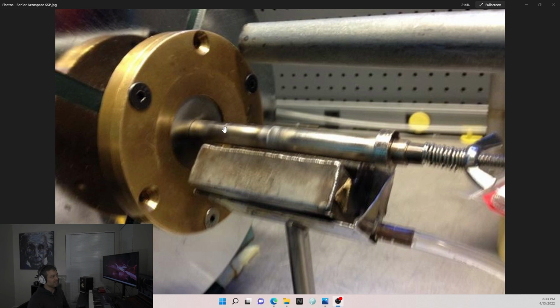So this purge inside the tube, you want to have tops 5 CFH when you're doing the tube to tube. When you're doing tube to plate, you want to have that at 2-3 CFH, so you don't get any suck back. That's more than enough purge for that. And then this bottom one, it varies. You want to crank it up, but to the point where it's not blowing the argon away from your torch. So 15, 20, you're just gonna have to gauge that with some scrap material, and as long as it's not blowing the argon out of your torch, you're good to go. So this is the weld test at Senior Aerospace SSP, the D17.1 weld test.